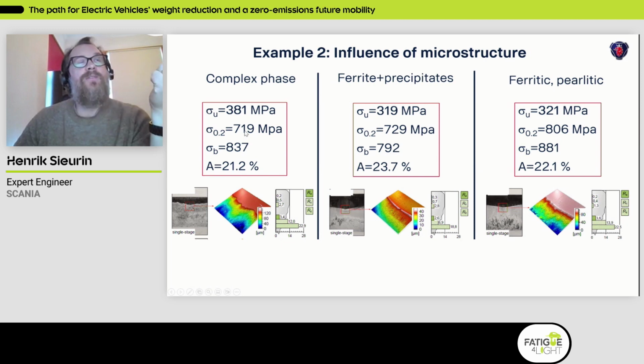And despite having the lowest yield strength, lowest ductility, the poorest surface, it had the highest fatigue strength, 380 compared to 320. So that's almost 20% better fatigue properties, despite these other factors that you would assume would give a lower fatigue strength.